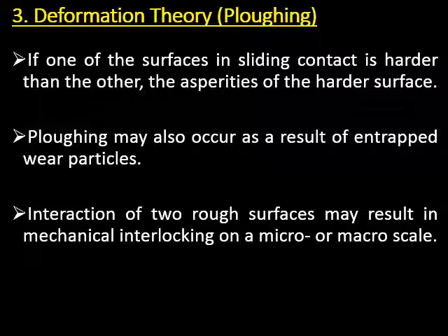In order to reduce this ploughing component of friction, it can be reduced by reducing the surface roughness, by using components or surfaces of the same hardness, and by reducing the possibility of forming wear particles, or by removing the wear particles from the interface.